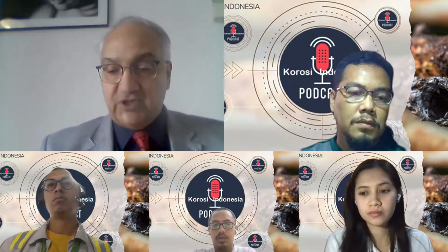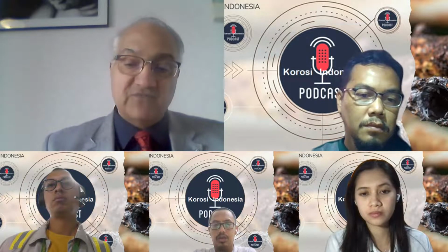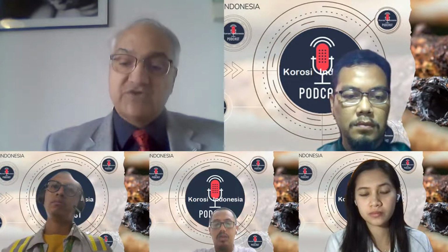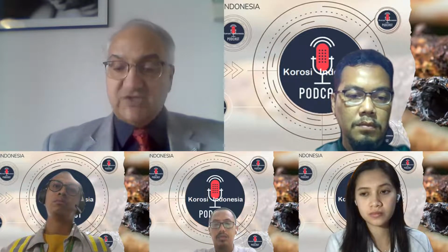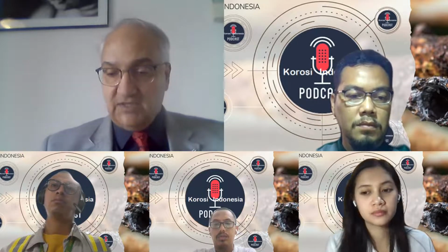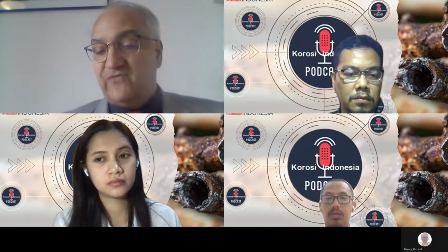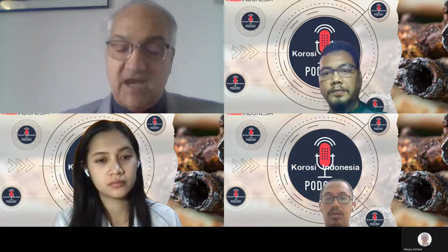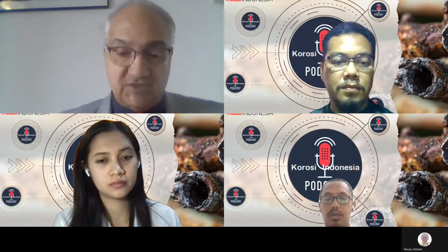In my publications and classes, I always advise that when you have a case of corrosion and you think it could be MIC, first try to explain it in terms not involving bacteria. Try to explain it in non-MIC terms. And only when you fail, then try to involve bacteria. Because if you do it the other way around, it is highly likely that you make a mistake and you may even make the conditions worse. Sorry for the interruption.